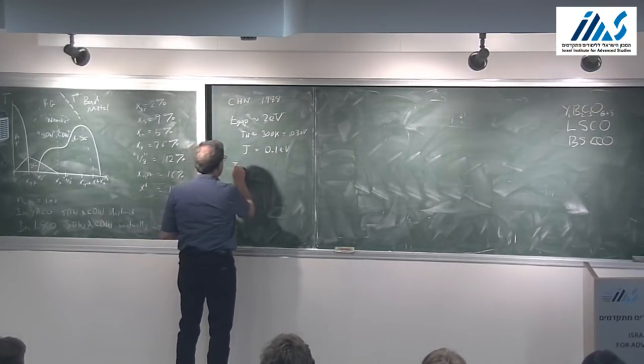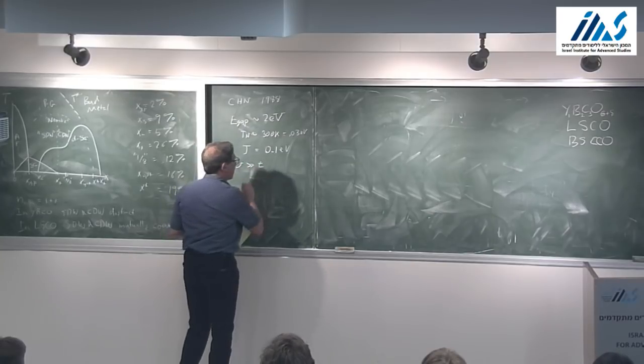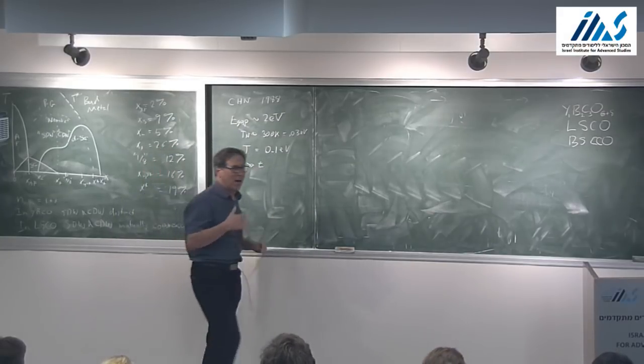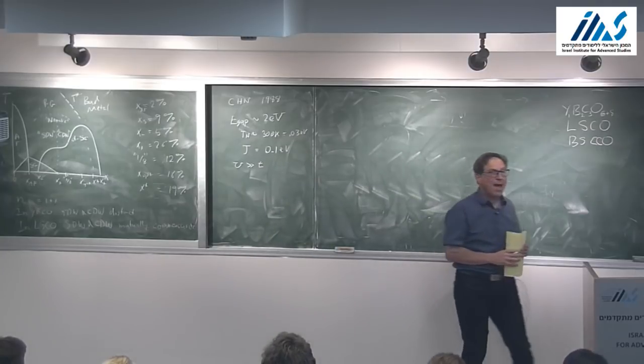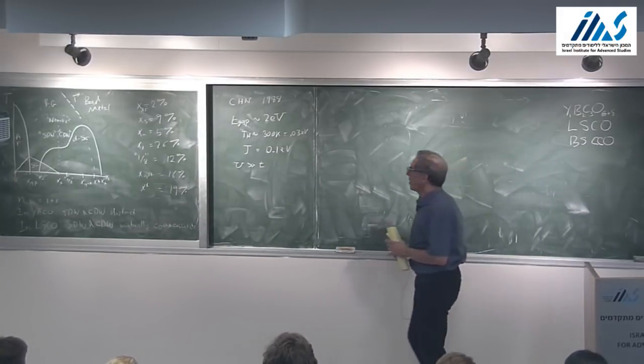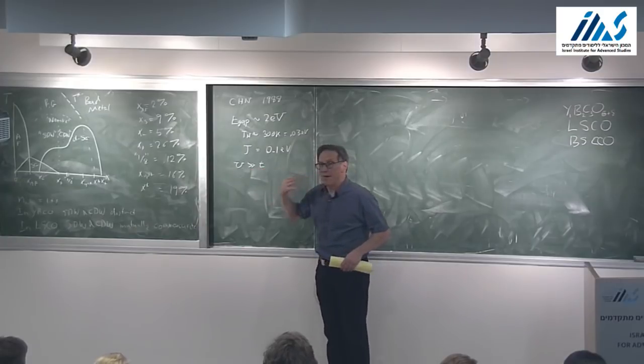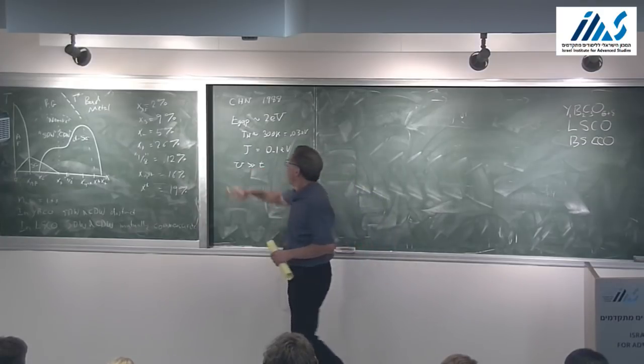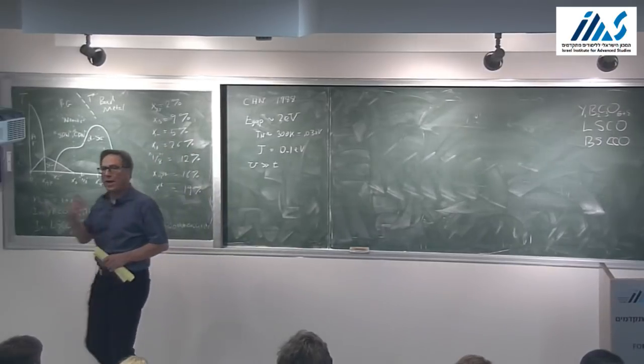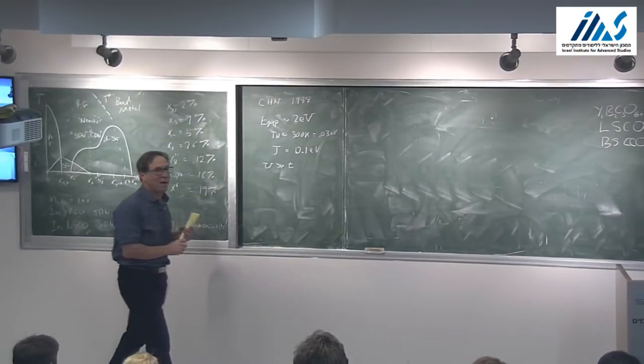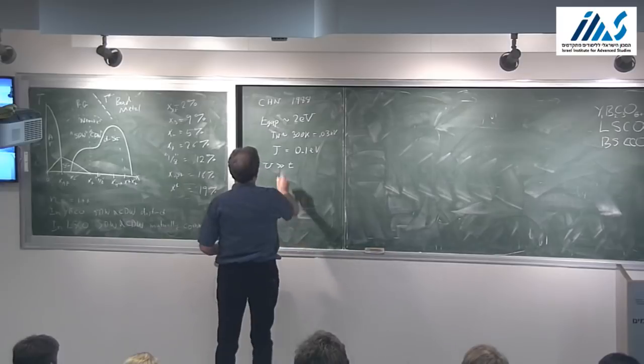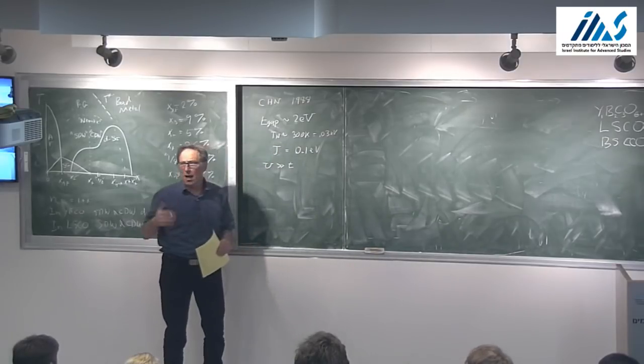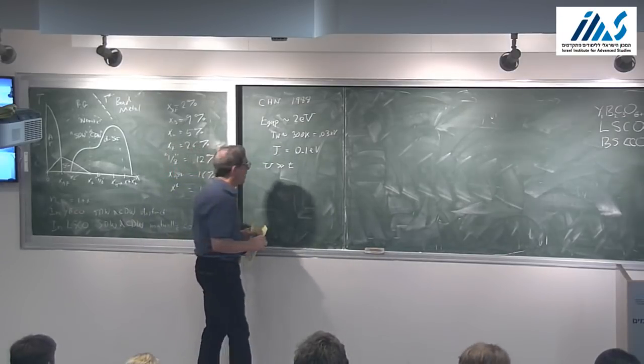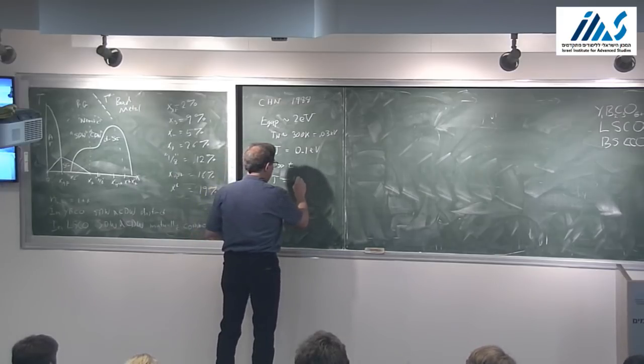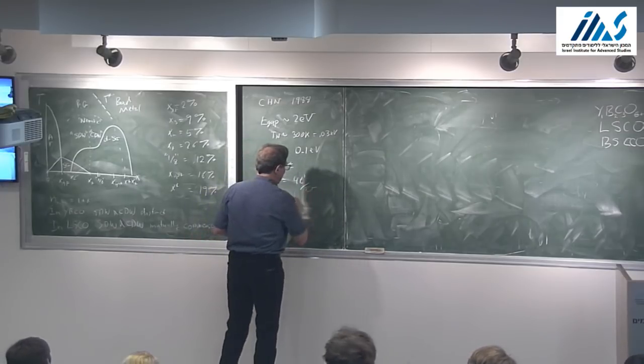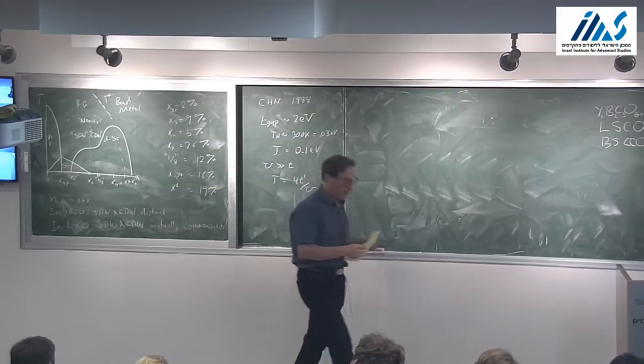So at least for this, we clearly want to take a strong coupling approach to the system. We want to imagine notionally that we think about this system having a very large U on each site. Then at temperatures below the gap, we can think of this as being a spin-a-half Heisenberg antiferromagnet, and J is some antiferromagnetic exchange between nearest neighbor spins, which we might think is something like 4t squared over U.